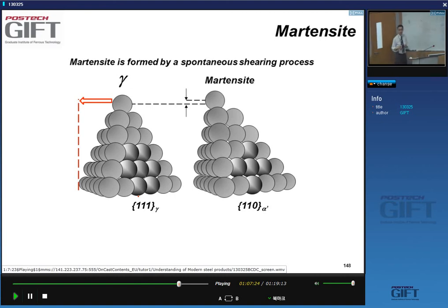This is the martensite start temperature, but we also have a martensite finish temperature, right? Because I need to cool down enough to get the full transformation. It depends very much on the composition of the steel, but as a rule, if you don't have much information, the MF temperature is about 100 to 150 degrees lower, right? So 100 to 150 degrees, that's the MF. Yeah? So if I have austenite here with this much carbon, I cool down, martensite transformation will start at this temperature and will be finished at this temperature. And here at room temperature, I get 100% martensite.